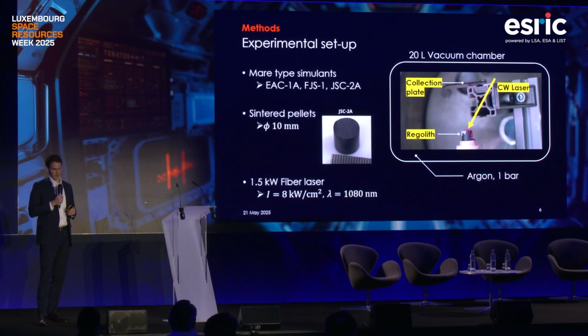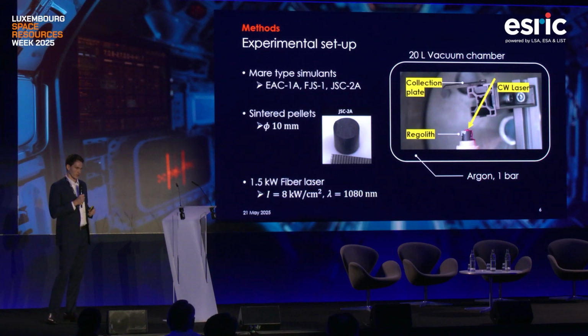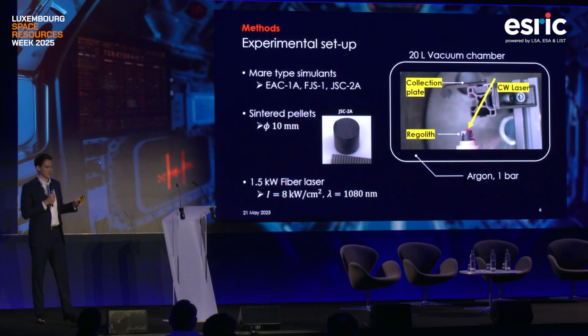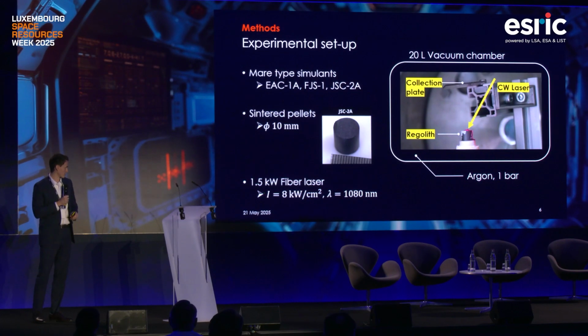So this is the idea, and we tried this doing some experiments, not on anorthite or anorthosite, but on Mare type simulants for now, being EAC1A, FJS1, and JSC2A. We took the powder and sintered them into solid pellets, mainly for the convenience of the experiments, and placed these into a 20-liter cylindrical vacuum chamber. You can see a close-up of that in the picture. We mounted a collection plate on the top to adhere the species that we extract through this method, and irradiate the laser onto the sample.